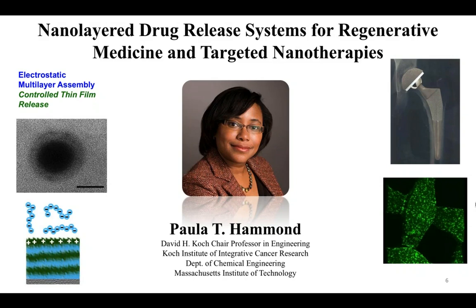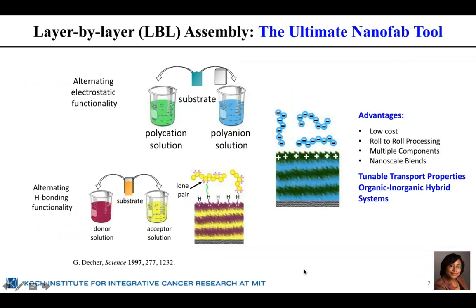I'm really excited to talk to the group today and describe some of the things that we can do with layer-by-layer assembly. I'm going to focus on our work in biomaterials and how layer-by-layer assembly is a very fascinating route for drug delivery. Layer-by-layer itself is a very simple process which involves the alternating adsorption of positively and negatively charged species onto a substrate. So, for example, one might imagine a charged substrate, something as simple as a glass slide that can be immersed into a dilute aqueous solution. If that slide is negatively charged, then a polycation, or positively charged polymer, can adsorb onto that substrate until ultimately the surface charge is reversed. Upon rinsing, you can remove anything that's not truly adsorbed, and then adsorb yet again another oppositely charged material, and that will adsorb until surface charge is reversed. And that process is repeated again and again.